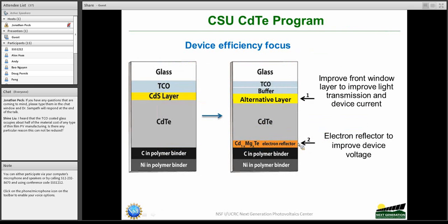So I want to briefly describe the CSU cadmium telluride program. This is the device efficiency focus, and then we'll later on talk about the packaging focus. So currently what we are engaged in is to take this layer, which usually was a glass with TCO with the cadmium sulfide and cadmium telluride, and we're working on two major improvements. One is an alternative layer, which we saw before was magnesium zinc oxide. It improves the front window layer, and that is to improve the transmission and improve the device current. And then this higher band gap cadmium magnesium telluride material, which we call electron reflector, and the purpose there is to improve the device voltage.